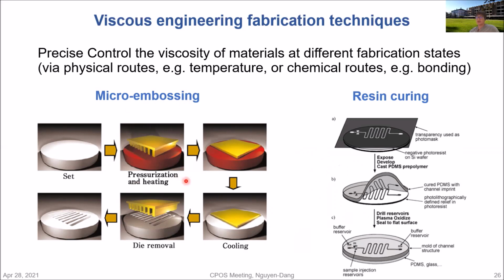The viscosity of the materials can be controlled by annealing, increasing the temperature physically. So the viscosity will decrease, which allows you to push a stamp on and then remove the stamp. By cooling it, the viscosity will increase enormously, so there will be no deformation. And now by removing the stamp, we will have the microstructures.